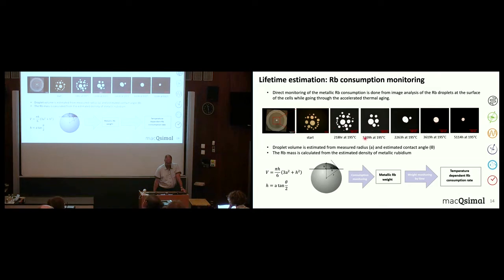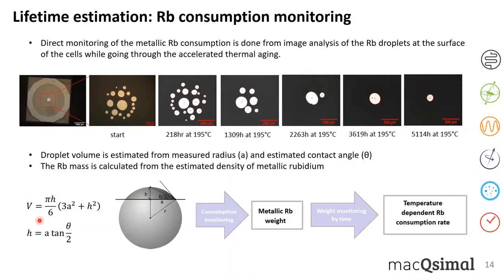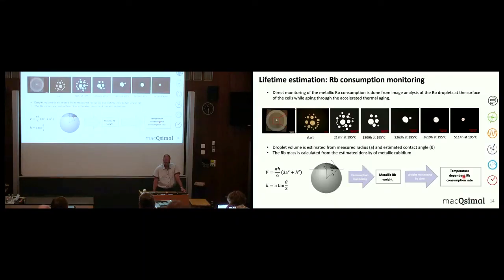If we analyze these images, we can calculate a theoretical radius, assuming that the droplet is round. We have also measured the height of these droplets by white light interferometry. With both pieces of information, we can extract the volume per droplet, and knowing the density of rubidium, we know how much metallic rubidium in weight we have in the cell at the beginning and how this disappears over time. So this allows us to establish a consumption rate of the rubidium which is temperature dependent.